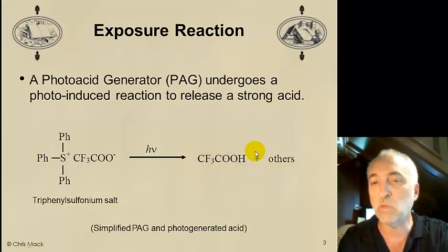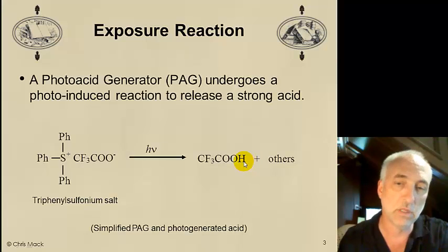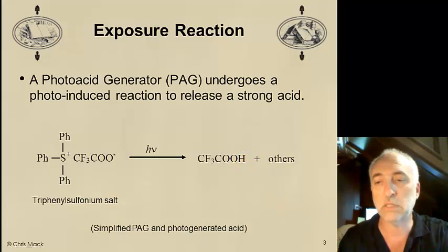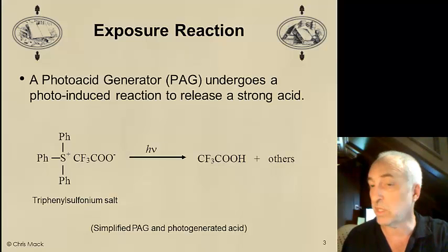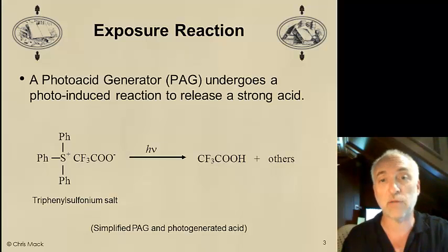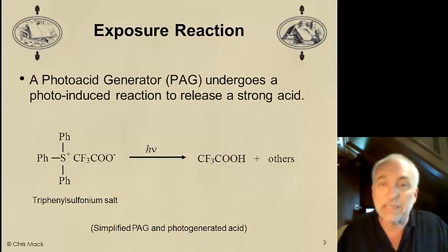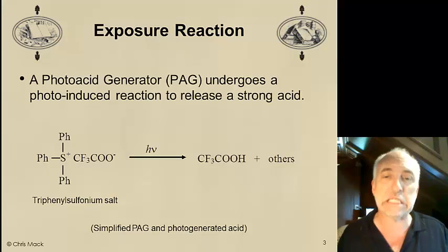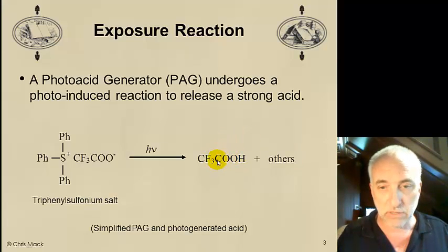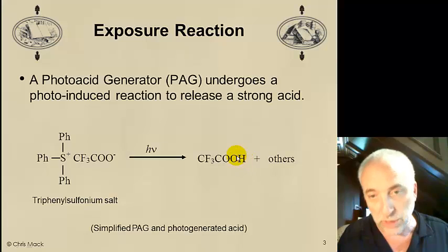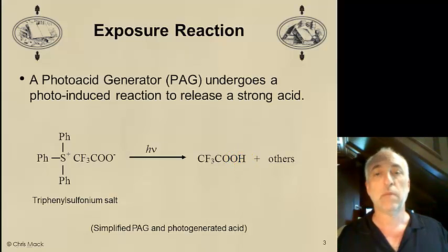Carboxylic acids tend to be weak acids. Think about acetic acid. DNQ resists generate very weak acids in their carboxylic acid. But this acid is not weak, it is strong. The electron withdrawing properties of fluorine tend to grab up all the electron density and pull it over to the fluorines. So over here in this carboxylic acid group, there's not much electron density left to hold the hydrogen in place.